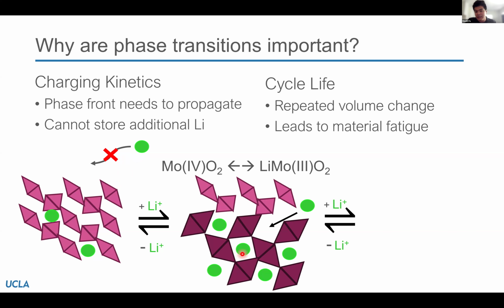This process is known to limit charging kinetics because, like I mentioned, you need to nucleate and grow this phase, which is known to be a slow process and often rate limiting.